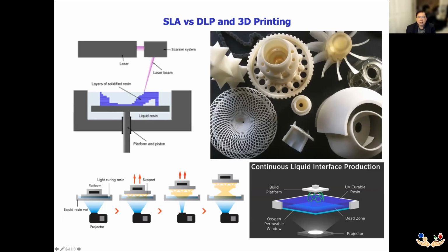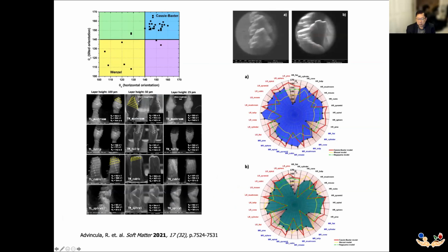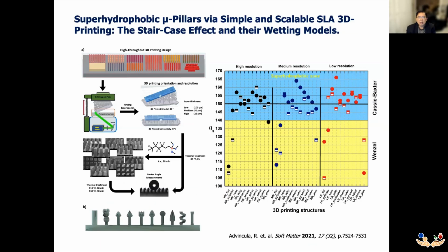So as a technique, this can actually go to even higher resolutions. In this case, we did a project that involved the design of different surface features as shown here by SLA. The question we were trying to answer was, can we produce super hydrophobic films on surfaces simply by 3D printing? Indeed, we looked at various types of features from spears to coil to square to a Mickey Mouse. And we found that at the right combination of factors, they produce a super hydrophobic effect based on the